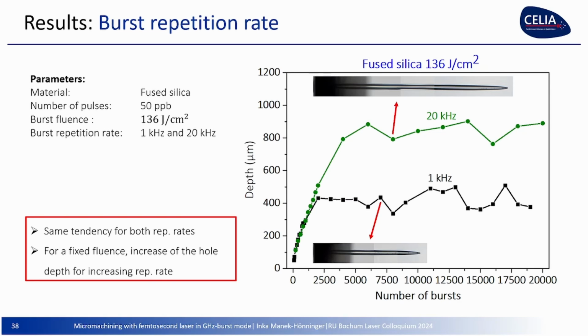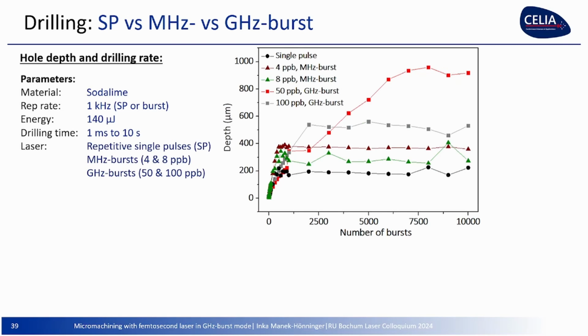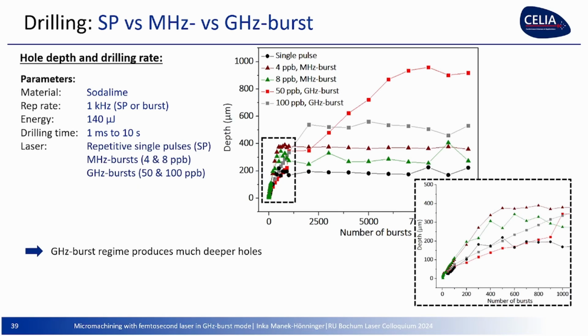Now let me show you some comparison between single pulses, megahertz bursts, and gigahertz. So there's quite a lot on this graph. Once more, now you're used to it, you have the drilling depth as a function of the number of bursts. And here, black dots are single pulses, triangles correspond to megahertz bursts, and squares correspond to gigahertz bursts. Okay, you can see many things. You can see, of course, in the gigahertz burst regime, you have deeper holes. But you can see, we reach them later. And if you have a closer look on this first part, which gives the drilling rate, or the slope is the ablation rate, you have a higher ablation rate in the megahertz burst. But it is somehow logical because you have more energy per pulse in a megahertz burst than in a gigahertz burst. So you drill faster in megahertz burst, but you go much deeper in the gigahertz burst.